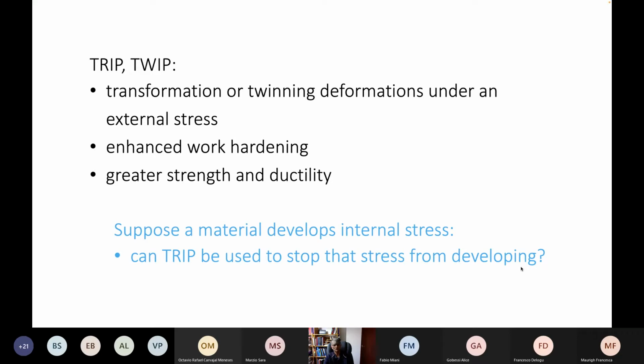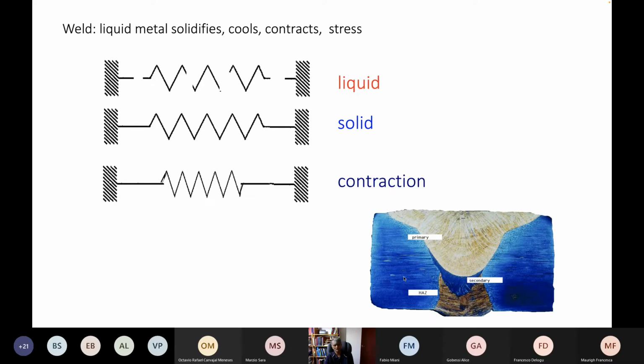Okay, I want to show you an example where transformation-induced plasticity is used to stop the accumulation of residual stress as large components which are constrained are locally heated or cooled. So welding is an obvious example because we take two bits of steel and in between we put liquid metal, the liquid solidifies, and if your component is large, then these parts don't really want to move as the weld contracts, and therefore you accumulate stress.